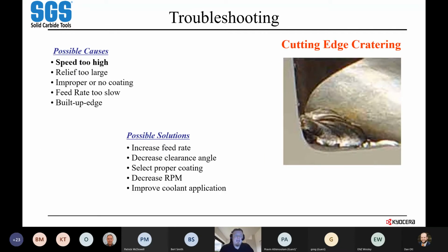Cratering on the edge. Cratering on the edge almost always is caused by too high of a speed. Ultimately, this is heat and pressure. So you're building up too much heat in one spot on the tool. It could be because your relief is too large. There's not enough meat behind there that's really causing the heat to dissipate through. Could be from a coating issue, whether the coating flakes off, you didn't have the right coating, or it could just be an uncoated tool that you should be running coated.